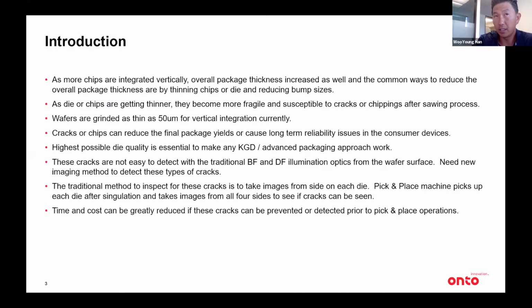So in the last 5-6 years, we've been getting a lot of requests from our customers for detecting die cracks, right? And that's because in the industry currently, these chips are ground down. It's very common to see wafers ground down below 100 microns, and we are seeing wafers that are even thinner, below 50 microns. As these are as thin as below 50 microns, they become more fragile and susceptible to cracks and chippings, right?